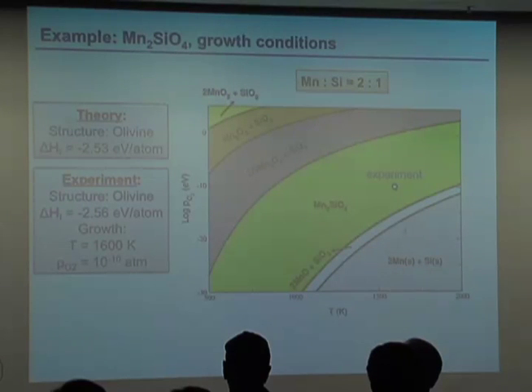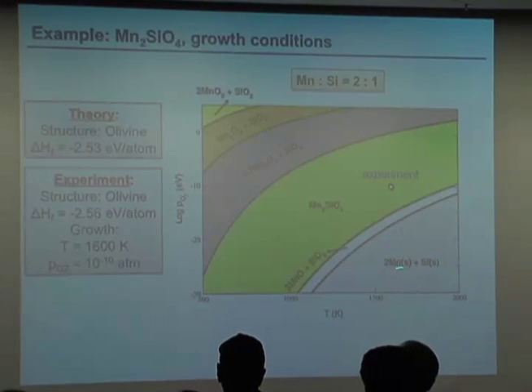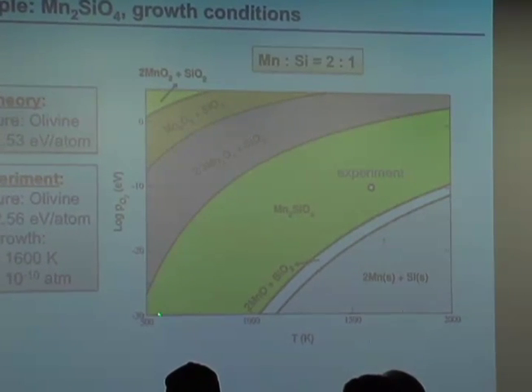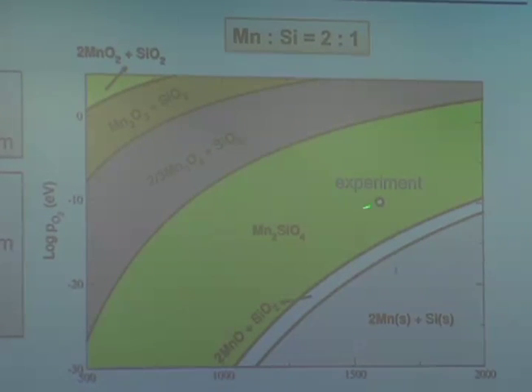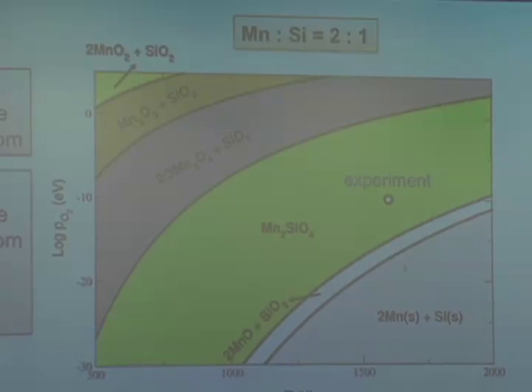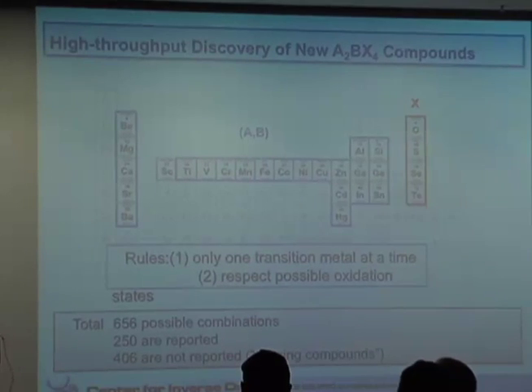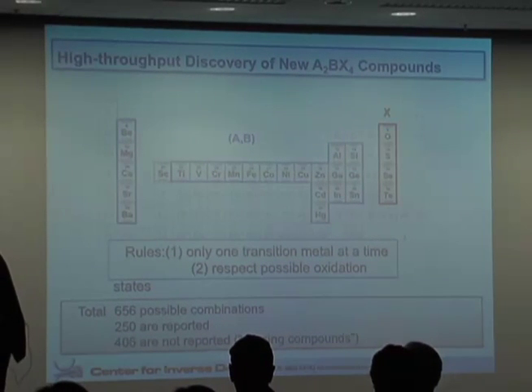Mn2SiO4 is stable. Here's where it's not stable with respect to the elements. Here's where it's not stable with respect to other oxides. So this window is that little box we defined. And in fact, that is where that experimental point fits in that processing window. So that becomes a very important tool for theory to help understand where to make things. And so now let's try to see what we can find.